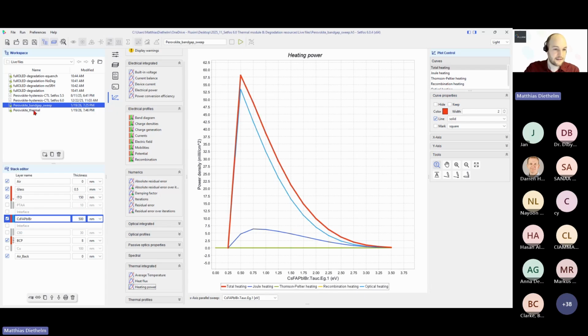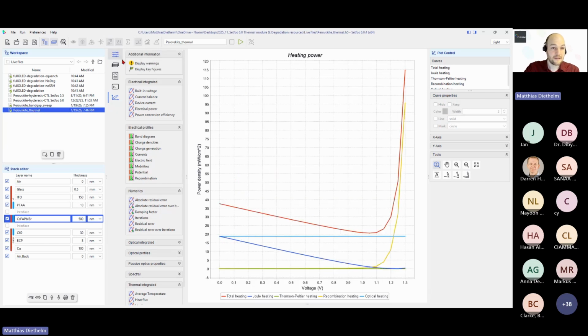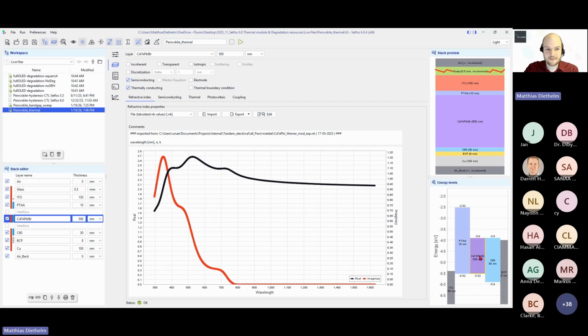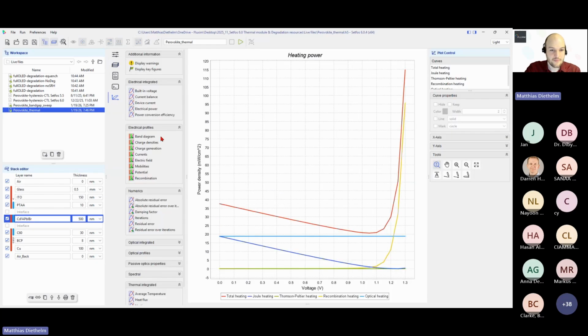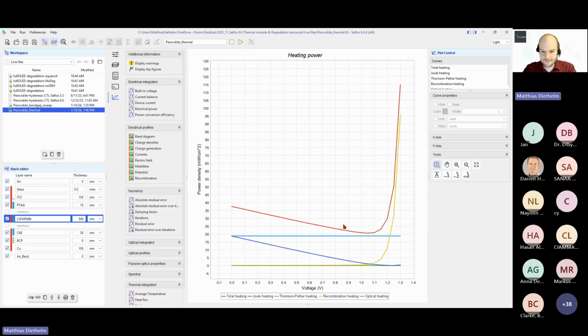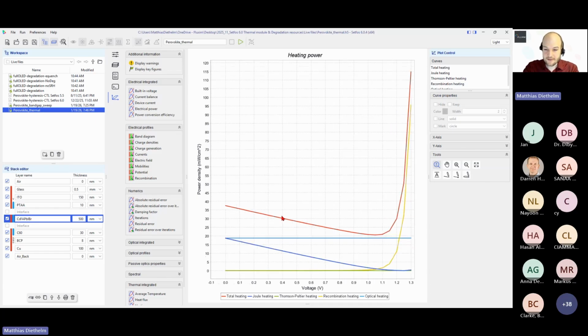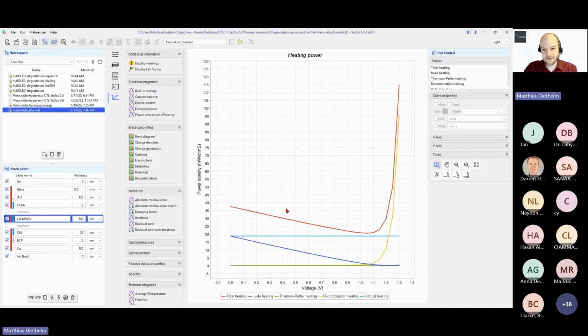So if we have a look again at the full model at a higher band gap of 1.6 eV, you see here again with the transport layer simulated and injection barriers, along with some Shockley-Read-Hall recombination. If we look at the results of this simulation, you can see here that the power that is lost in heat, the heating power, has quite a peculiar shape when looking through the swept voltage from JSC, short circuit, towards VOC, and that's because the Joule heating is getting comparable to the thermalization.